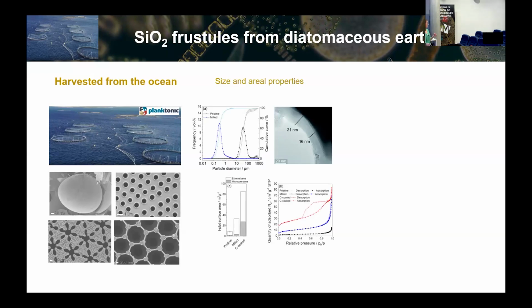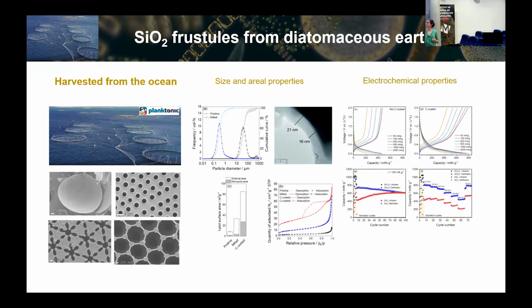So we did essentially the same thing we did with the previous one. We do the ball milling of the material. We try, of course, to increase a bit the area. We did the coating with the processes we already have developed for that. And then we did the cycling. Still, we have to do the activation steps, although in this case it was not as relevant as before, but still we have to do it. This, I think, is intrinsic to the silica, or at least that's the feeling we have so far. And the capacity starts with good numbers, but then we have capacity decay over time, again typical of this silicon issue.